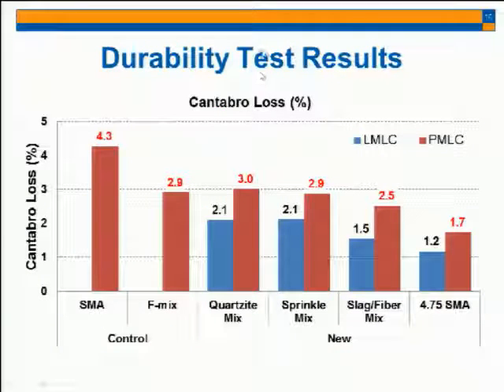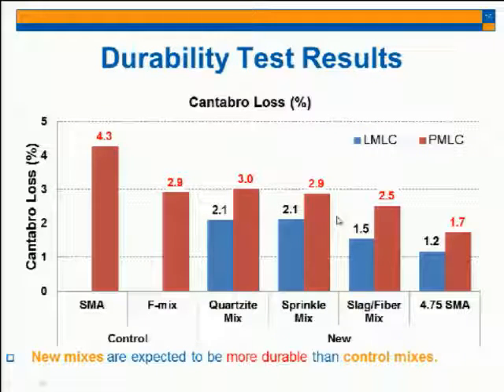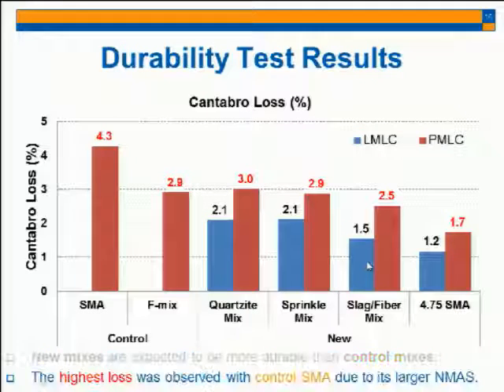So if we have the higher number here, that means it's less durable. As you can see, new mixtures are expected to be more durable than the control mixture. And also the highest loss was observed with the control SMA because of its larger nominal maximum aggregate size. As you can see, this is the 12.5 mixture. The four mixtures in the middle are 9.5. The last one is 4.75 SMA. But again, this 4.75 SMA had a higher asphalt content. So this provides the least loss of the materials after 300 times of rotation.